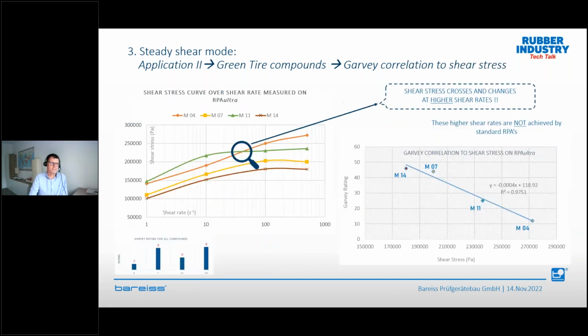So we ran a steady shear test, and I would like to explain this graph. What you have here is the shear stress as a function of shear rate. Here are our 4 samples. Remember, the orange one is sample number 4, which has the very bad processing behavior on Garvey because of linear polymer and silica silane. And if you look at 14, it's much better, a branched polymer and a carbon black. If you go to lower shear rates, as normal instruments do, this means Mooney. Look at the shear rate at 1. This is Mooney. Mooney gives the highest value for sample number 11. But this is in Garvey a completely different information.